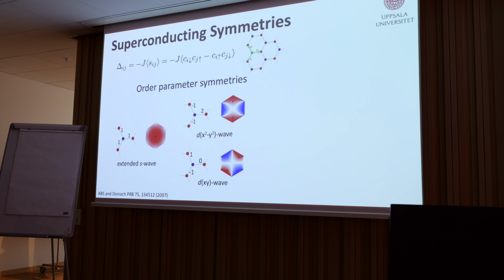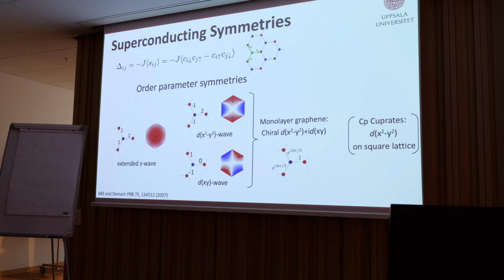There are two d-wave solutions. One in real space looks like this. So you have the order parameter twice as big on this bond and a minus sign on the two other bonds. Fourier transform that to k-space, and it looks like a d x squared minus y squared. And then you have a dxy version that looks like this in real space and like this in k-space. So that's why we call it dxy. These two d-wave solutions, because they're four-fold symmetric on a six-fold symmetric lattice, are actually degenerate. They belong to the same irreducible representation. So you can very easily combine them.